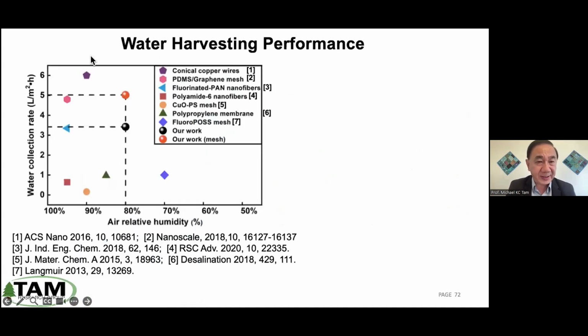So we compare our system with the conventional system. In this case, at 80% relative humidity, our material here has about 5 liters per meter square per hour. So every hour, if you have a meter square of your surface, you can collect 5 liters of water. That's about how much we consume daily.